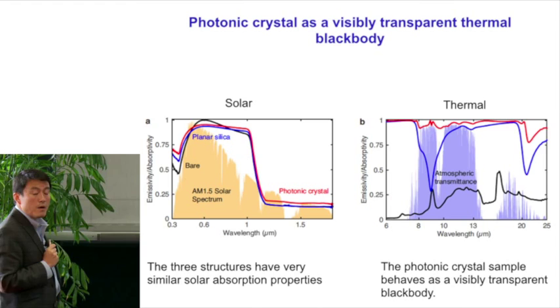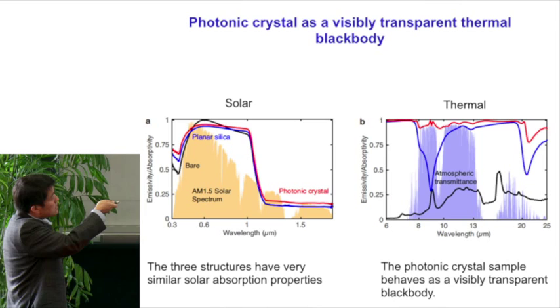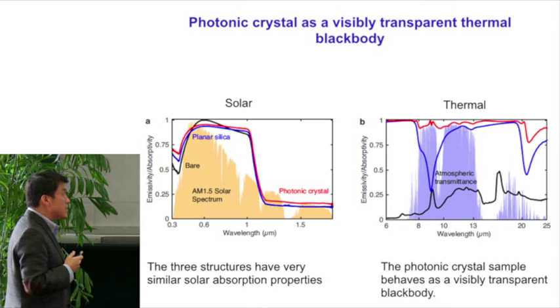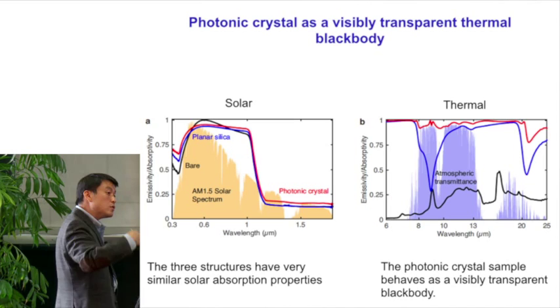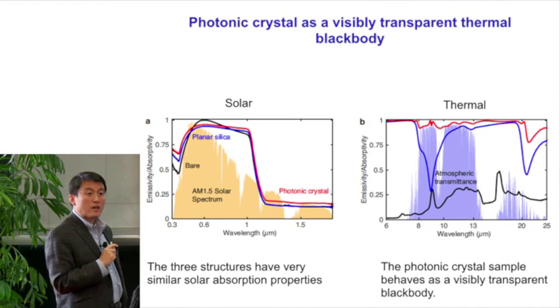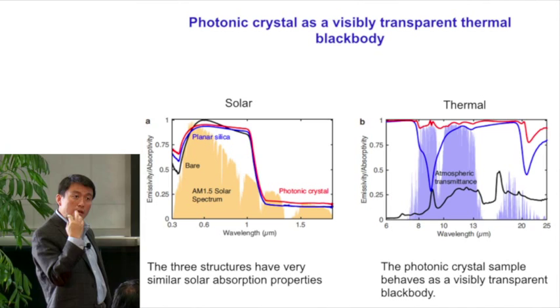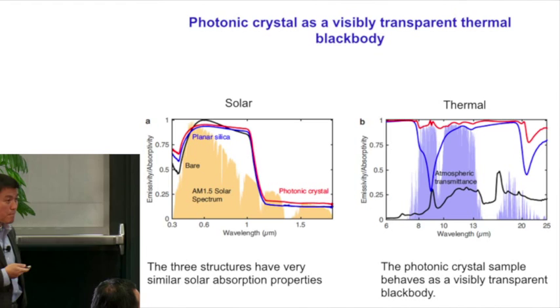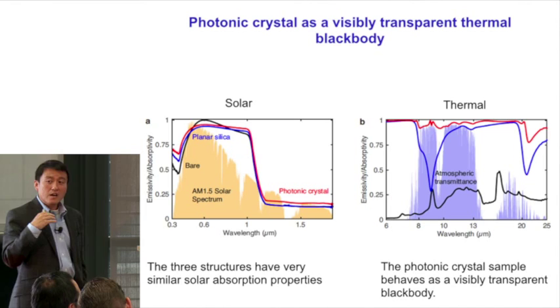The red curve here is the silica photonic crystal thermal emission spectrum. In this case, it has an emissivity that's near unity due to the use of the photonic crystal. So what we have created here with the silica photonic crystal is actually a structure that's visibly transparent. It looks like any regular glass, but it behaves as a thermal black body, which is a somewhat unusual structure compared, I guess, with your typical view of what a black body would look like.